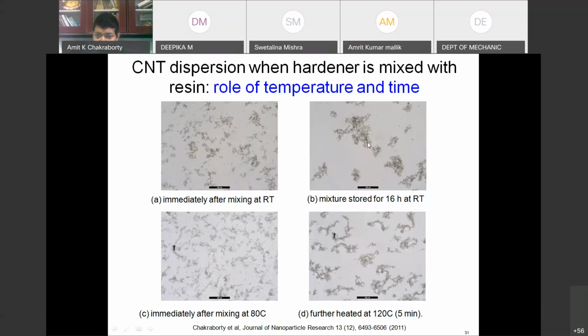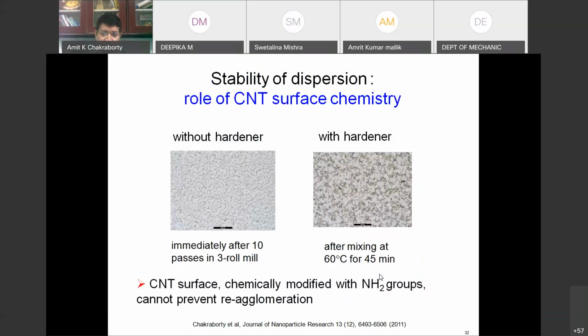After 16 hours, it is even worse. See large chunks of material and large regions where nothing is there. This is slightly better at 80 degrees, but this is again slightly worse because it is higher temperature. Why is higher temperature worse? Because as you heat, the resin viscosity lowers. If the resin viscosity drops, what happens? The particles become more mobile and they can then come together and find each other, make friends with themselves. That's how they re-agglomerate. So these are the challenges that one needs to address.